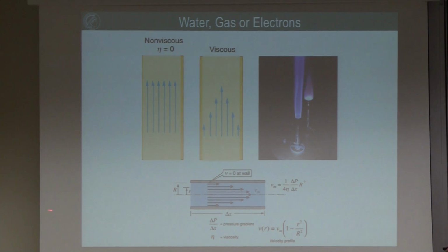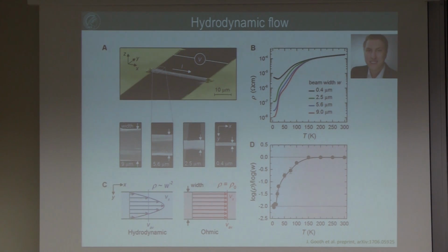You can do exactly the same with the electrons. Okay, so we did this. We had different widths of crystals because it was easy to split them, and then we measured here the conductivity. We did it in a pseudo 4-point measurement, but we also did a 4-point measurement as a control. And you see exactly at the temperature where you see this deviation with the magnetoresistance effect, you also see a deviation as a function of width. This we already saw in niobium phosphide.